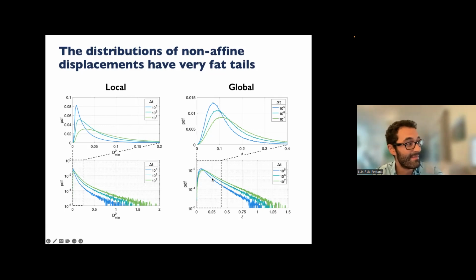Now, what you see in the bottom is the logarithmic scale in the y-axis in probability. Why? Because here you can clearly see that these distributions of displacements are characterized by very, very fat tails. This is important because it tells you something about the physics of the system. How people have interpreted this is that if you look at the tails, they start taking over when the probability is just below 10 to the -3 or 10 to the -4. So what this means is that most of the particles, 95% of the particles, actually undergo very small rearrangements. Their displacements are pretty small. And then some particles move a lot, and those are the ones that constitute the fat tails. So the fat tails here are very significant.